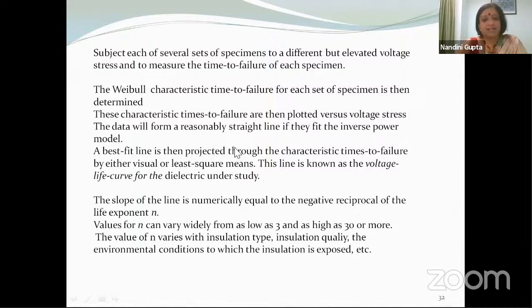The best fit line is then projected through the characteristic times to failure by least square means, and this will give you the voltage life curve for the dielectric under study. And using this, you can estimate the lifespan of the insulation under study. The slope of the line is numerically equal to the negative reciprocal of the life exponent n.